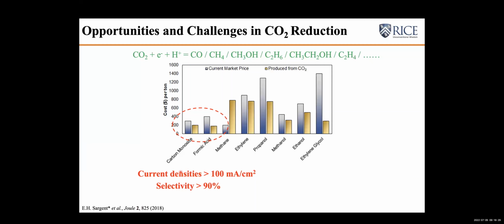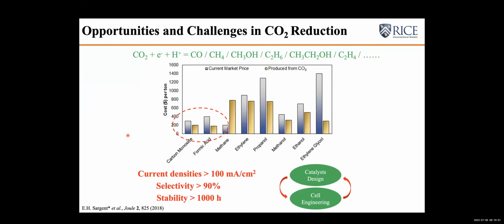And the most important and most challenging part is that, while maintaining these 2 very strict parameters, you have to run for an extended lifetime. In commercial water electrolyzers, the minimum requirement is 10,000 to 50,000 hours of continuous operation without changing the catalyst or membranes and so on. But here, as a very general requirement, more than 1,000 hours of stability testing is generally needed to make economic sense.